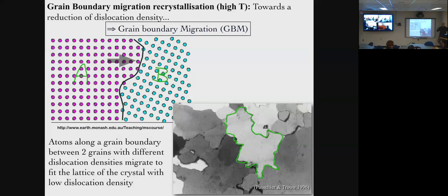Bulging is very localized just on the grain boundary and will produce new growth, new crystals. So if you look at the texture here, this is grain boundary migration, so it operates along the entire grain boundary. Bulging would produce little new grains right at the grain boundary instead. Okay?